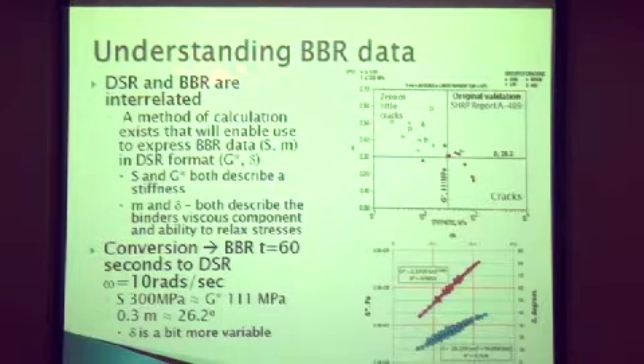In terms of understanding the BBR data, what we should note is that the BBR and the DSR, they're both rheometers, and we can take data from the BBR and convert it to the same format as the DSR data. So we can take the S and the M that we get from the BBR, and we can convert that to a G star and a phase angle, or vice versa. This is called interconversions. So the stiffness at 300 megapascals is basically the same as a G star at 111 megapascals. The 0.3 M value that we use is the same as a phase angle of 26.2 degrees. This is the original calibration of the low temperature cracking. These were the points that failed, these were the points that were okay.